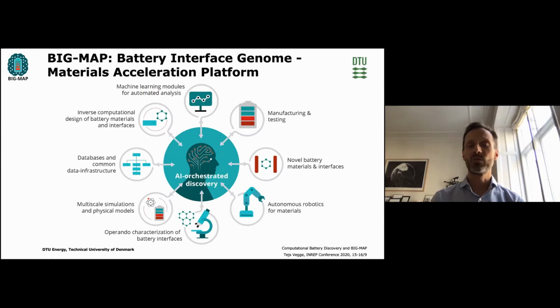So let me give you one brief example. So we can take a structure, either from our previous presenters, titanium sulfide, or a material predicted from simulation. We can then go in and use that information about the stoichiometry and the structures from the prediction and actually launch a synthesis directly, controlled by the AI. We can then automatically characterize that material if it turns out, and that characterization can be done using machine learning modules that automatically assesses whether or not we actually have the phase that we were interested in.